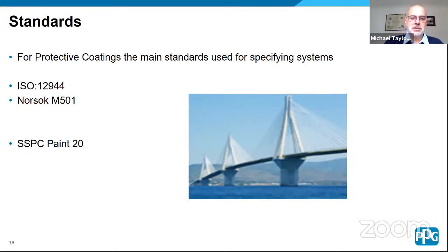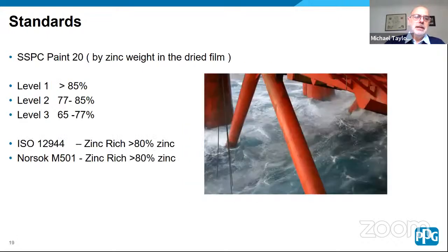The other standard you might come across with zinc coatings is the SSPC Paint 20. In the SSPC Paint 20, it specifies the amount of zinc weight in the dried films. It's got 3 levels. As you can see there, level 1 greater than 85%, level 2 77 to 85, and level 3 65 to 77%. The ISO 12944 classifies a zinc rich coating as something with greater than 80% zinc, as does the NORSOK M501. And that's where the vast majority of zinc coatings are, in level 2 of the SSPC.